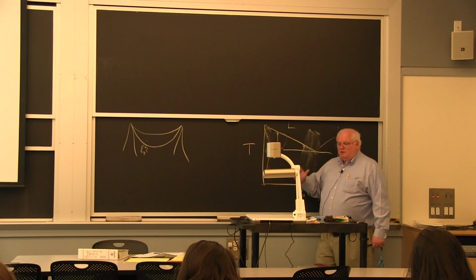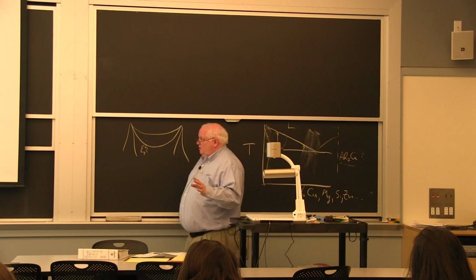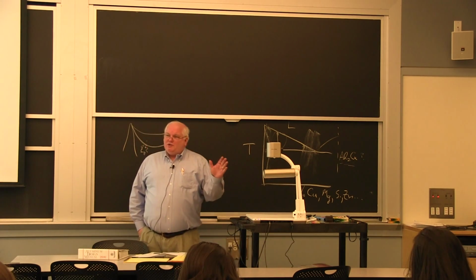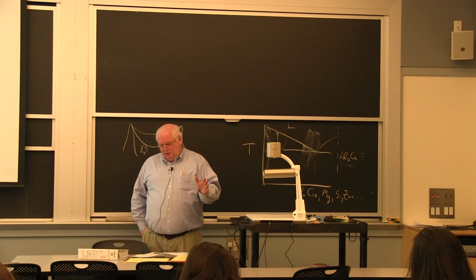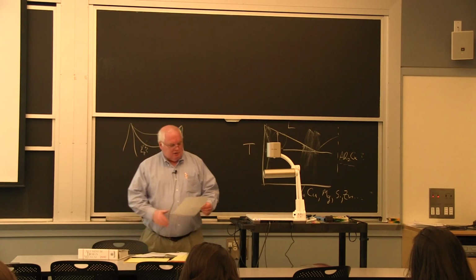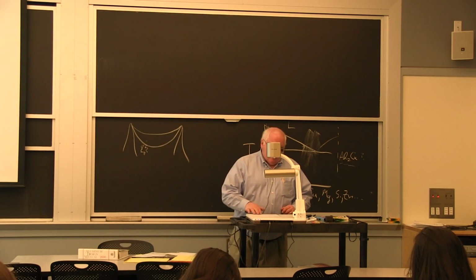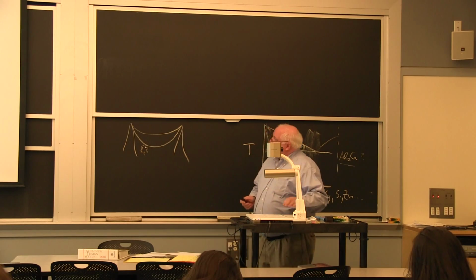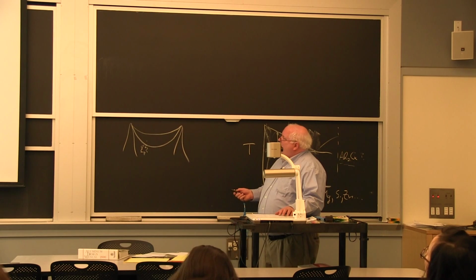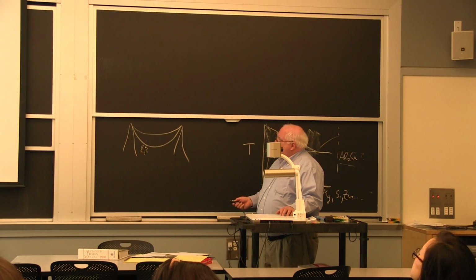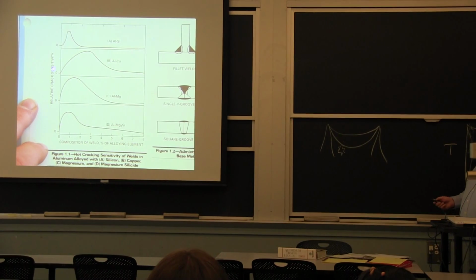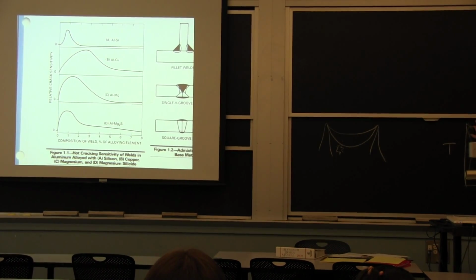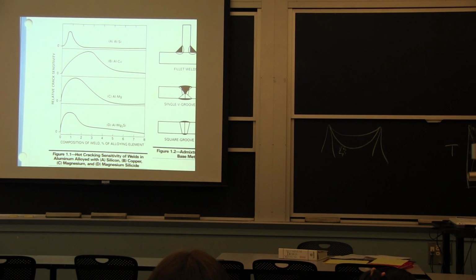And so you have to be very careful when you've got an aluminum alloy, even more so than steel in some ways. You've got to know what the composition of the aluminum alloy is before you select the filler metal. Okay? If you look at the relative crack sensitivity, that's what we're plotting here, of different aluminum alloys, silicon, copper, magnesium, magnesium silicide, you'll find this is composition of the weld of the alloying element, and all they're doing here is plotting the freezing range or the strain. Okay, it's alpha delta T. How big is delta T? This is basically delta T for this system.